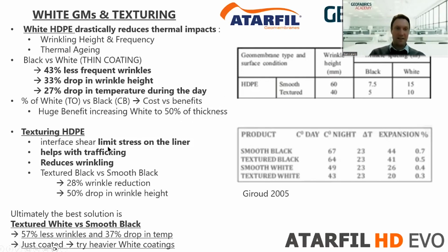And in terms of texturing, yes, you would use texturing if you wanted to place your HDPE or LL onto steeper slopes, but it actually helps with wrinkling as well. The chart on the right was done by Giroux back in 2005, and just through texturing, so textured black versus a smooth black, they found a wrinkle reduction of 28% and a drop in wrinkle height of 50%. It's good for installation, it's good for wind uplift, it's providing more intimate contact with your subgrade, which helps with flow rates through leaks. So there are that many benefits you get out of using the appropriate color material with maybe a texturing. And when you're comparing textured white to a smooth black, it's 57% less wrinkles and a 37% drop in temperature. So I'll move on from that, but I think you get the idea.